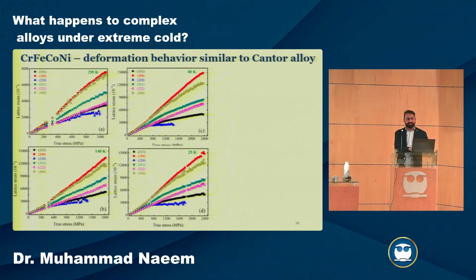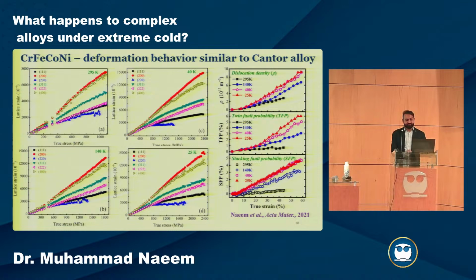And then again, this is what I've shown for a different alloy which had 5 elements, and now this is for 4 elements. So we started with 5 elements, and then we removed manganese, and this one also has quite similar behavior. And then we can quantify the contribution at different temperatures with stress. For example, dislocation density increases at low temperature, twin fault probability also increases, but it has very different behavior for 40 and 25 Kelvin, very close temperatures. And then stacking fault probability also increases at low temperature.